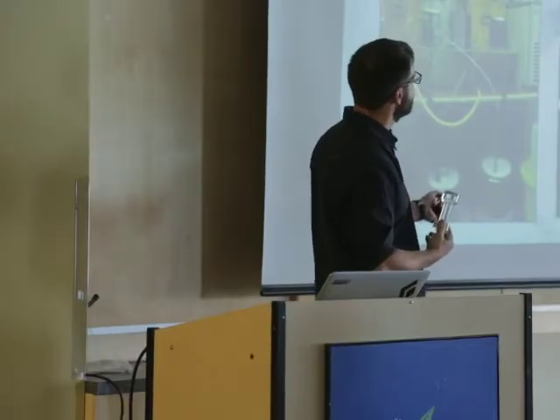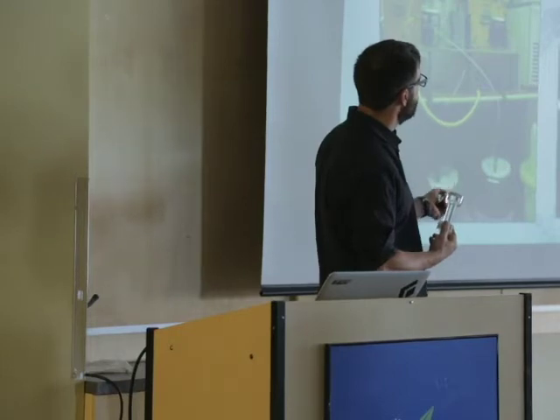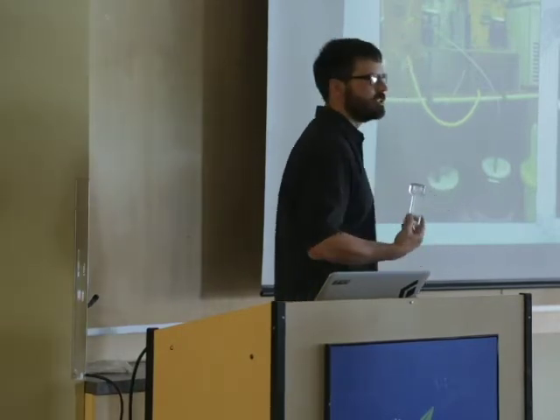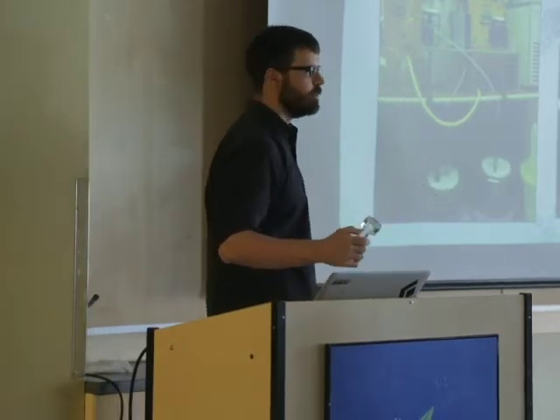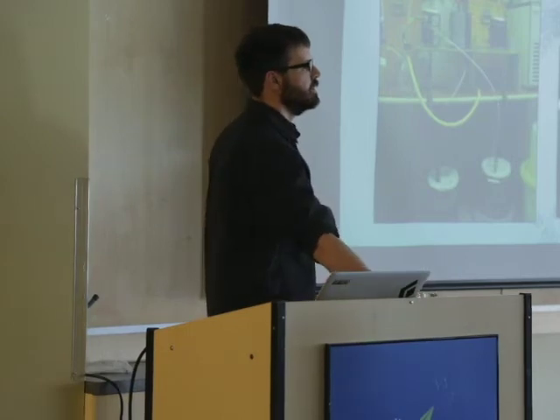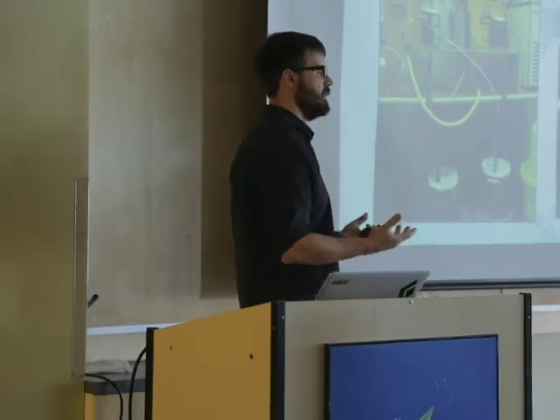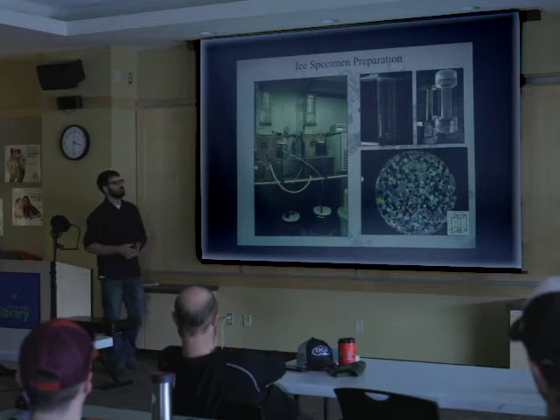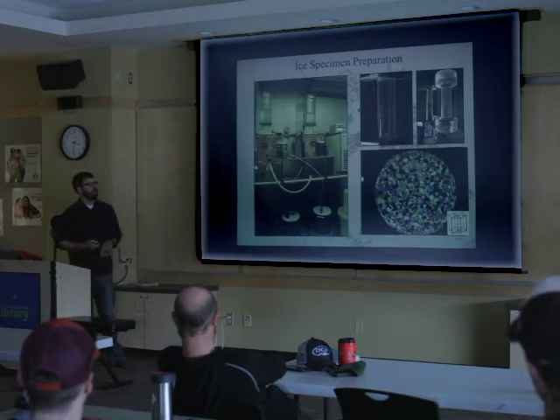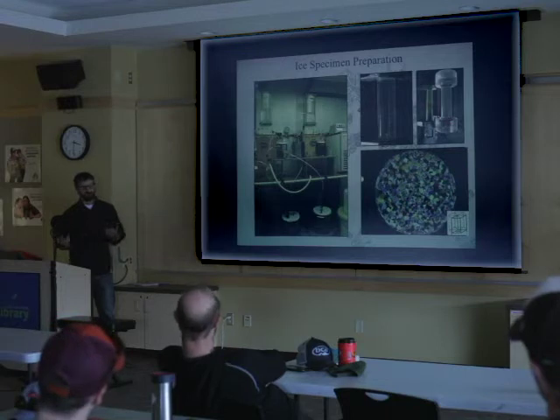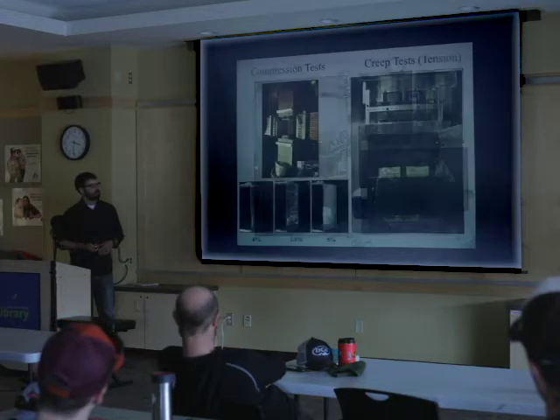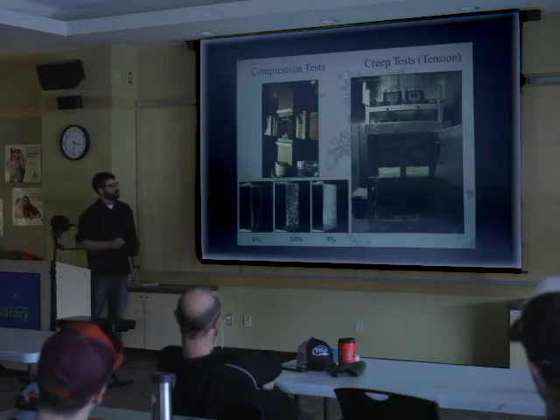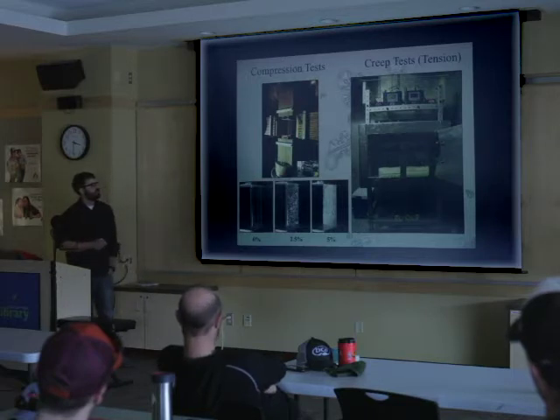So anyways, we were making these so that we could compress them and pull them in tension, doping them with very small amounts, like 10 parts per million, of sulfuric acid in one of these snow samples to be representative of nature. It's very, very trace amounts of sulfuric acid that's in natural rainwater and snow. So we're trying to mimic that, make ice, then do these mechanical tests to see how it affected the strength and the mechanical properties. To do that, we're using an MTS unit in uniaxial compression.